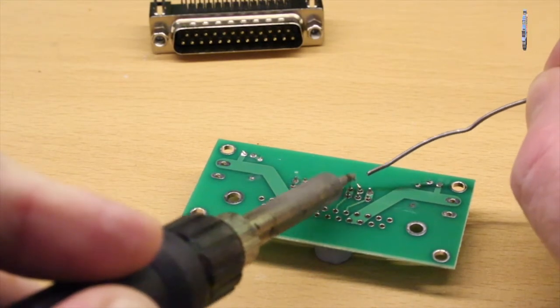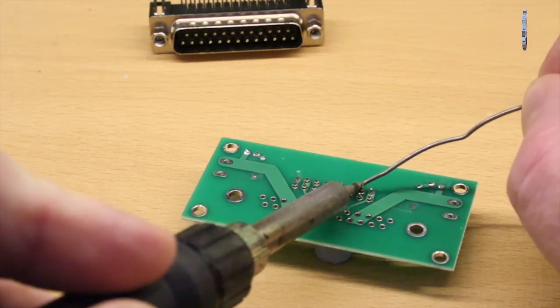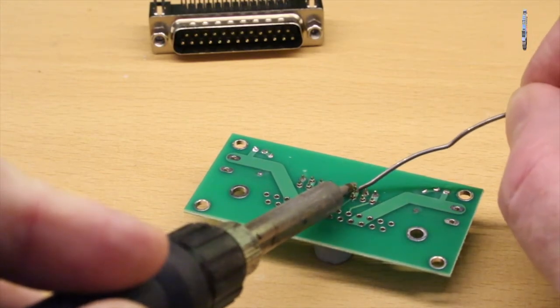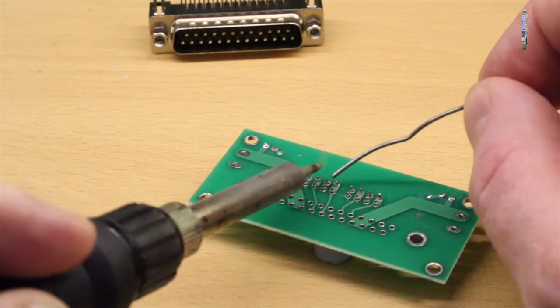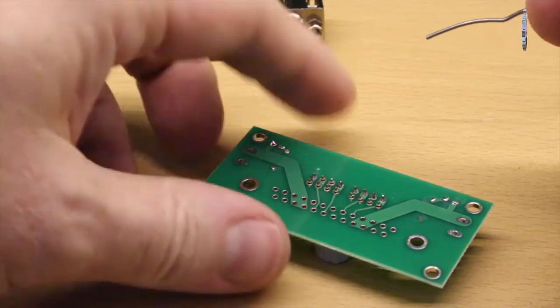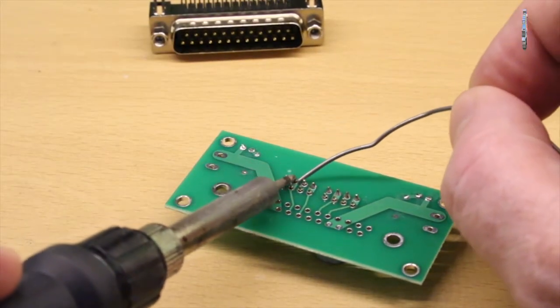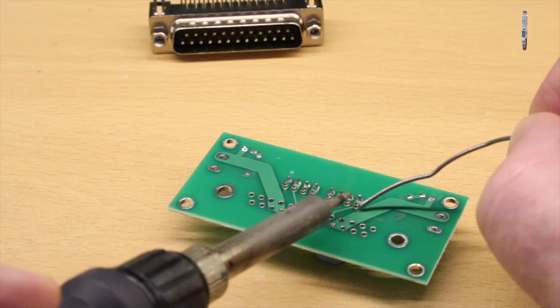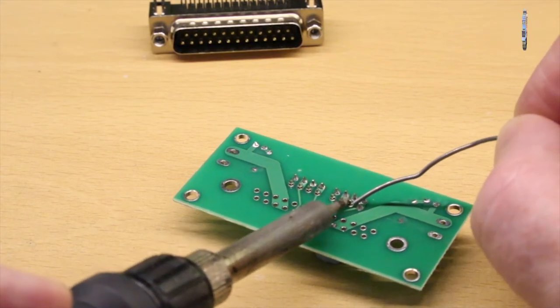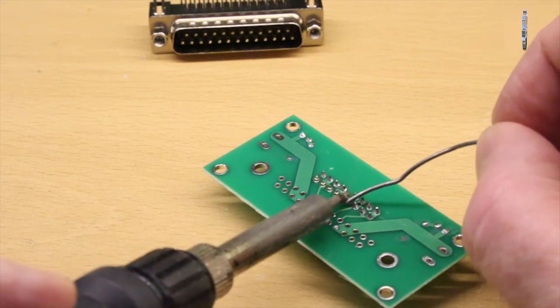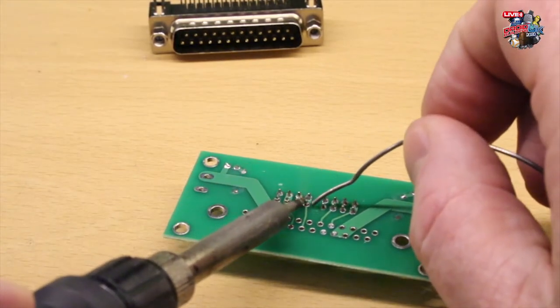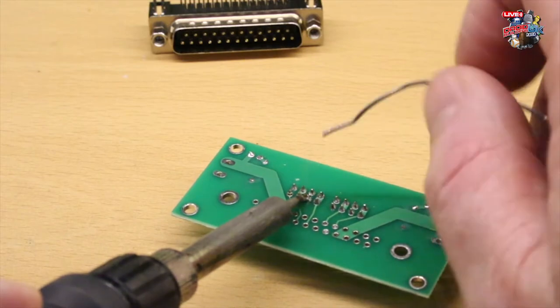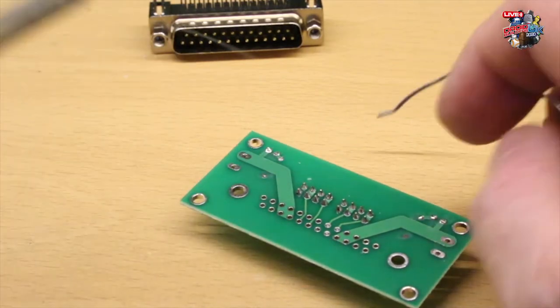But once you're happy with the one pin that's soldered, you can then go in there and solder all the others. Again, what you're doing with the soldering iron here is you get the soldering iron behind where you want to go, and I touch the solder onto the soldering iron and then move it over onto the component, because that ensures the solder starts to melt and flow before it then goes onto the actual components. If you can see, what it actually looks like is the solder will start to flow on the joint and then you'll see it kind of suddenly rush between the two parts, so it'll rush between the pin and the base underneath. And what I'll do in a minute, not on this one, my blue tacks let me down a little bit here, but it's still holding it in the right place. The thing is, once it's got those first pins soldered, it's not going to move, then the components aren't going to move anyway. Okay. And that is done.